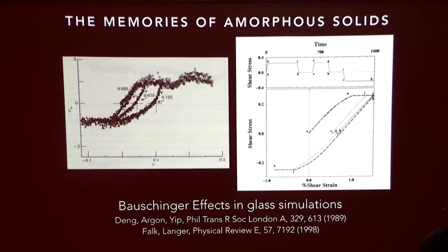So I'm a little slow, but what do you mean by softer - do they go to the same magnitude of shear stress in both directions? If you look for when it turns over, when it deviates from linear loading, that happens earlier in this direction than in this direction - at a smaller strain, a smaller stress. So softer doesn't mean a lower modulus, but an earlier onset.